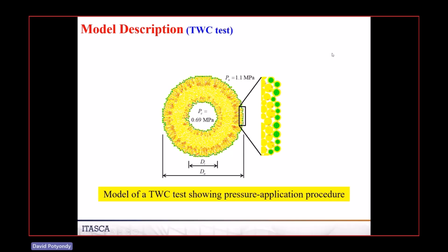This is the modeling that was done for that situation. This is modeling a thick-walled cylinder test where you take a cylinder of rock, you drill a hole in the middle of it. This is looking down on the cylinder. You put it in a triaxial cell, and you then apply, typically you apply no pressure on the boundary and you simply start to apply pressure on the inside wall. Sorry, that's incorrect. Typically you apply no confinement on the inside wall, and what you do is in your triaxial cell, you apply pressure on the boundary. And you keep on applying that pressure until this thing fails, okay?